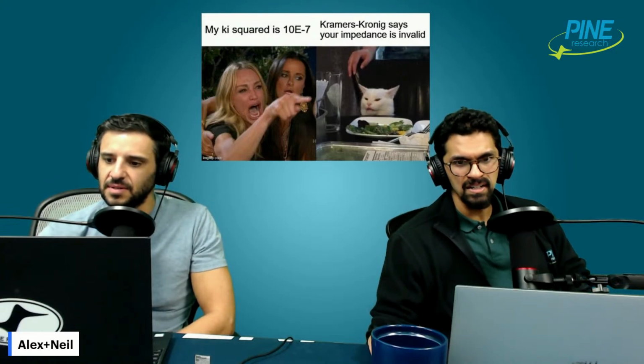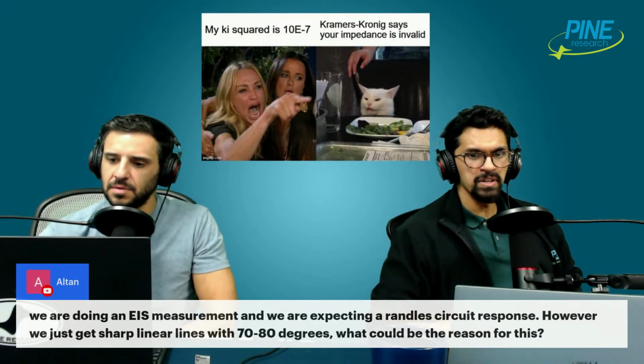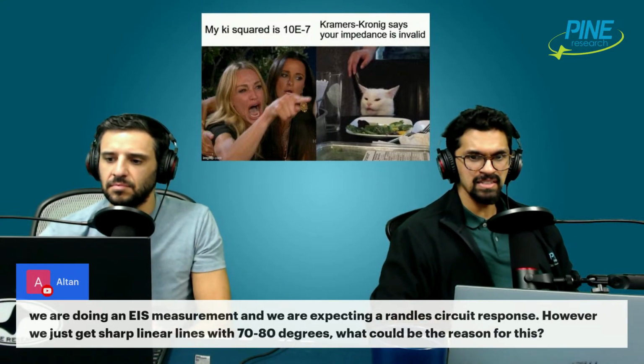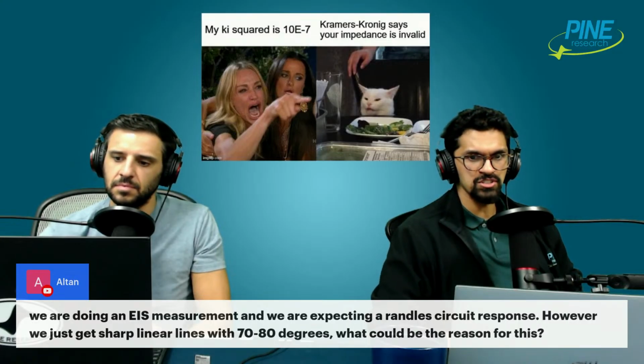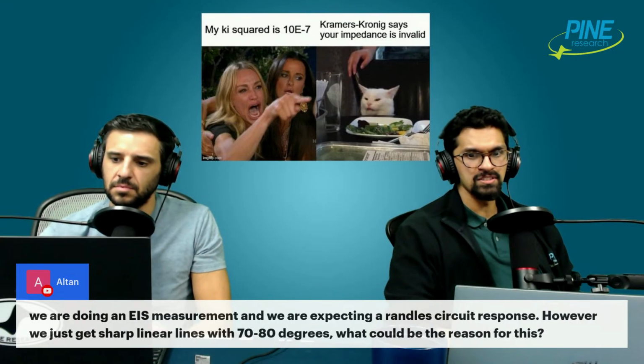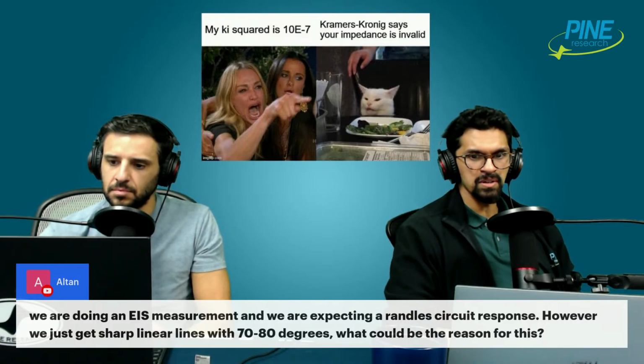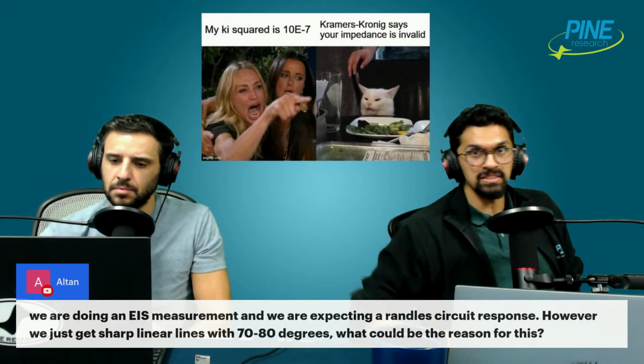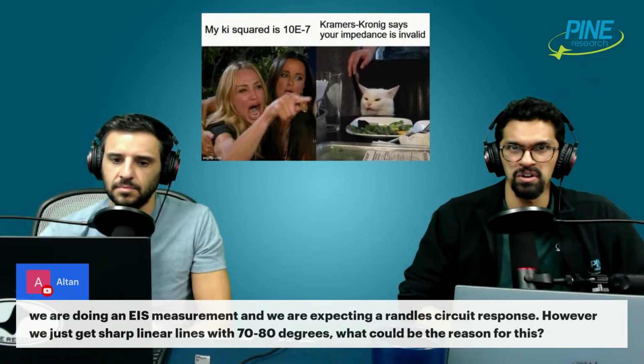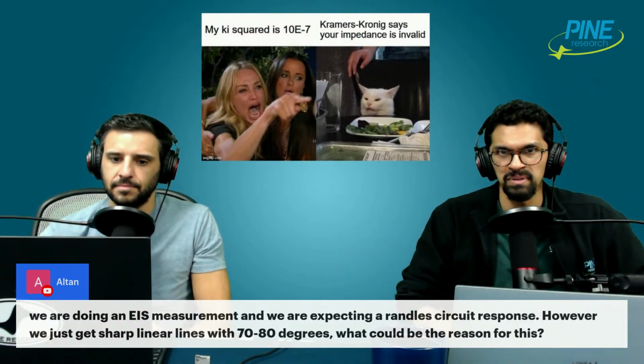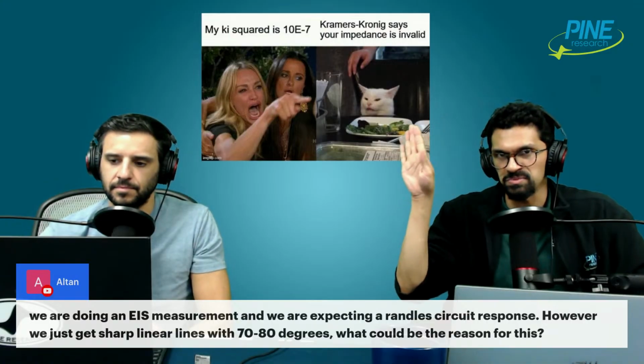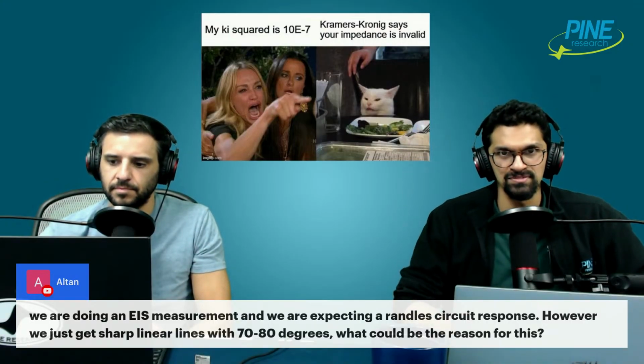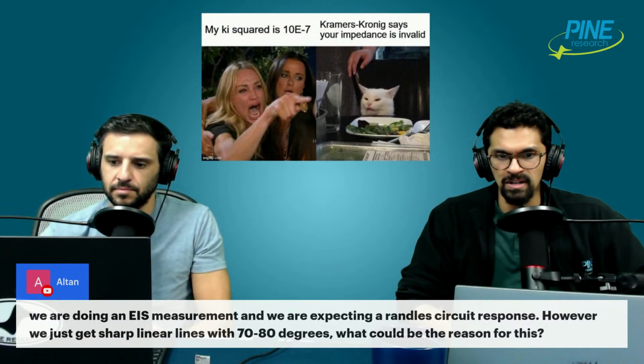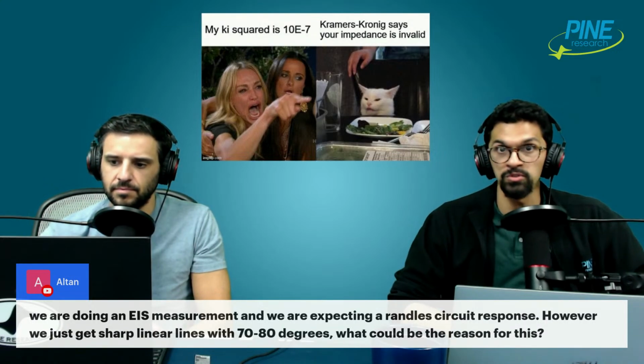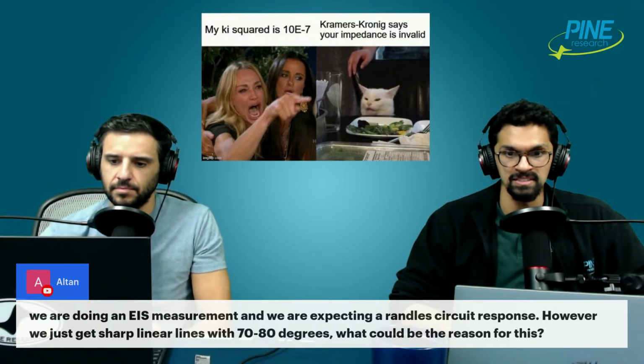Alton's asking, we are doing an EIS experiment and we are expecting a Randles circuit response. However, we just get sharp linear lines at 70 to 80 degrees. What could be the reason for this? So usually you get this kind of response. It sounds like it's more capacitive. The closer to 90 degrees the angle is, the more capacitive the system is. Also, this is assuming that the Nyquist plot is plotted orthonormal, with equal axis scaling.